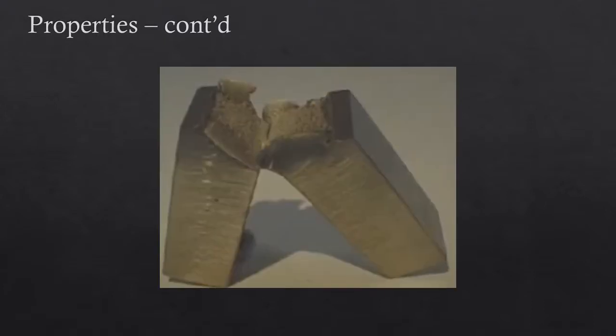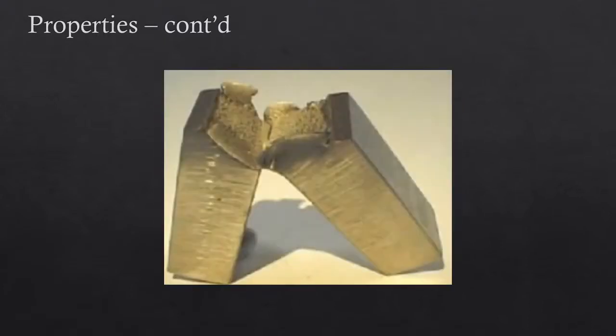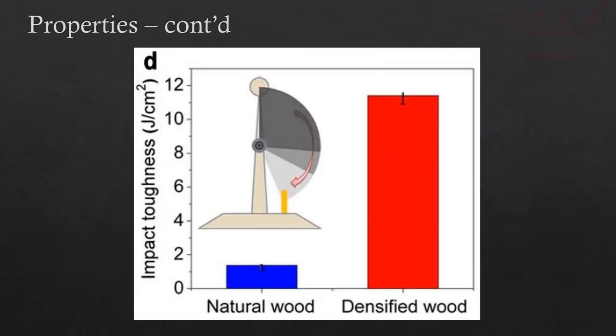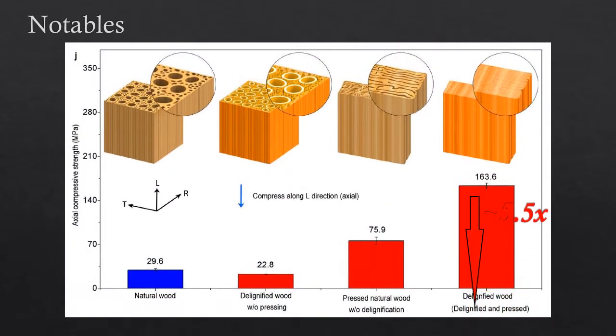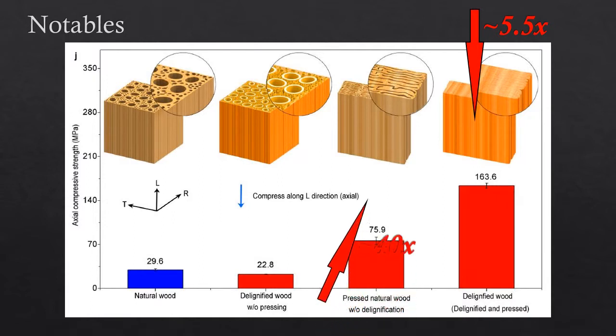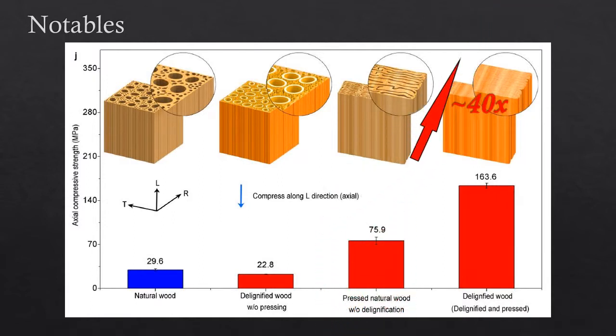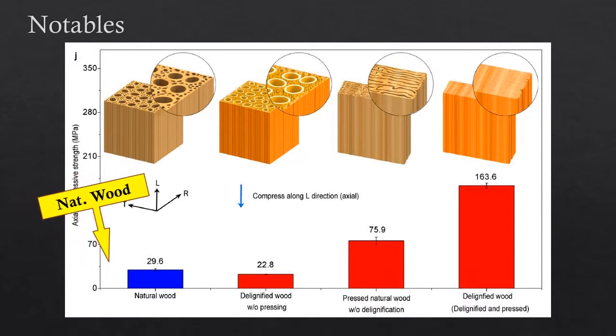Equally important to tensile strength is material ductility and resistance to impact loading. For this, a Charpy test was completed on the material. The test showed a mean impact toughness of 11.5 joules per square centimeter. This value is around 10 times higher than that of untreated wood, and it falls into the higher range for metals and alloys. This material even showed impressive results in compressive strength tests, with 5.5 and 40 times higher strength along and perpendicular to the wood growth than that of natural wood.